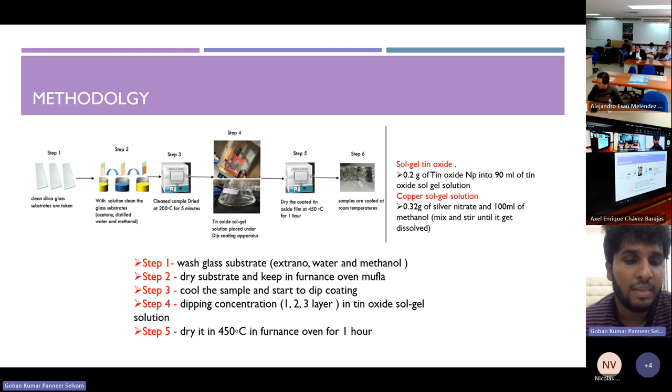take a glass substrate, and using the dip coating technique which I used in the laboratory, with a 30 second interval, I was dipping the substrate in the sol gel tin oxide solution, like one immersion, two immersions, and three immersions, which I made in the past research, giving thin films of tin oxide. The three immersions showed a good crystalline structure of the tin oxide, so I'm taking